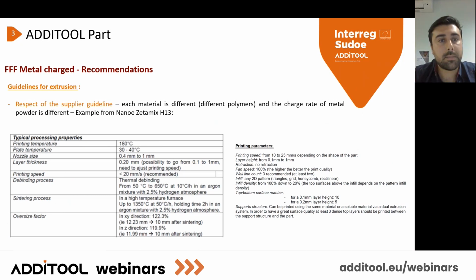Also, that is something good: we have some supplier guidelines. Each material is different, and we have different polymers and different metals. The charge rate also is different, and don't hesitate to take a look at it. For example, you have the conditions for debinding, the time, the ramp of increasing temperature. And we also have the oversize factor in the X and Y direction, which is 22.3%, and in the Z direction, you have only 20%. So it's different, so don't hesitate to take a look at it.